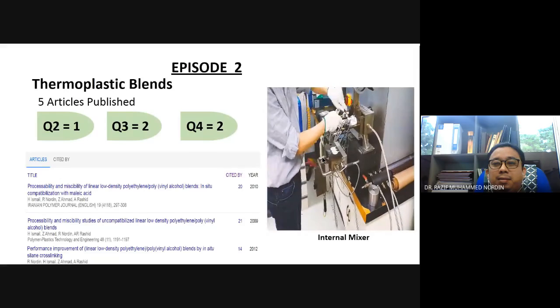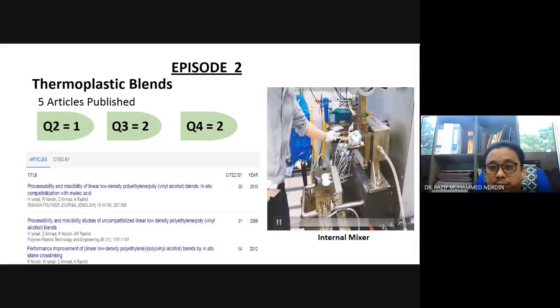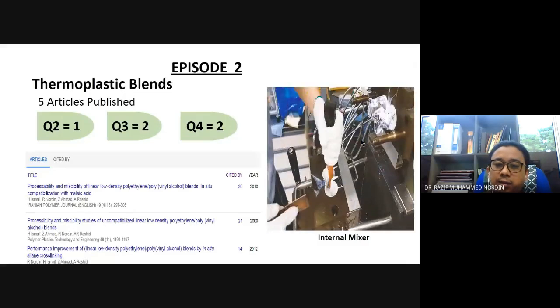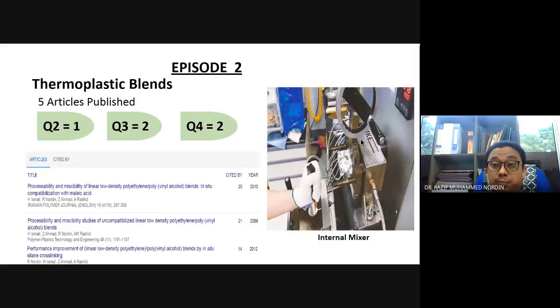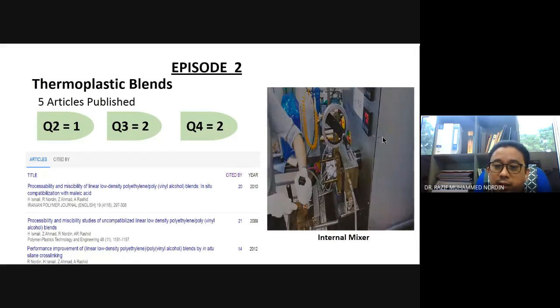But because you need to make sure the mixing chamber, this is a mixing chamber, is completely heated at 150 degrees, you need to wait about 1 hour. So the process took time, and then you need to do a cleaning process for every batch that you did. And the worst part is that per process, you can only produce about 45 grams. It is very small in thermoplastic technology. So because of that, I published just about 5 articles. So if you target to produce a lot of articles, you should go to rubber technology. It is very fast.